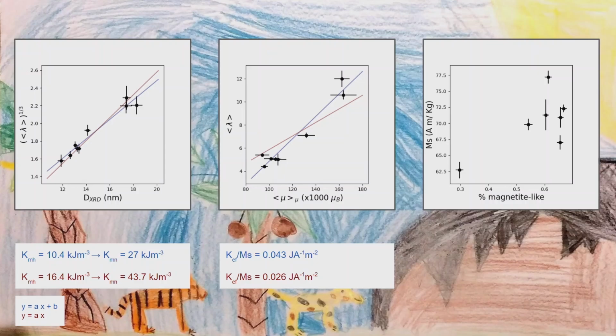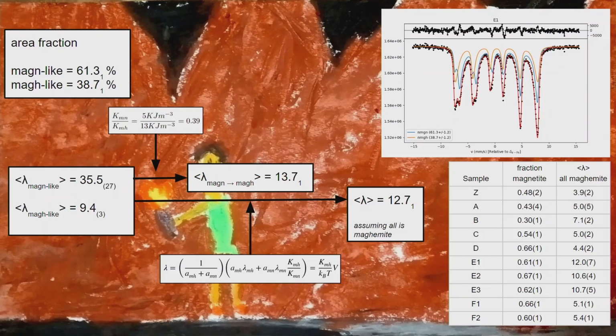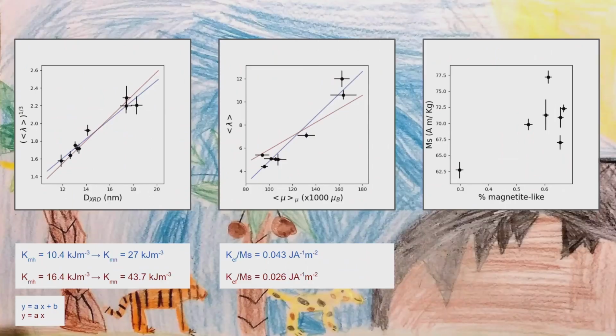From the correlation, we can obtain information about the effective anisotropy constant, and from the value we obtain, in fact, we obtain the effective anisotropy constant of the maghemite because of the construction. But with this easy or assumed relation, we obtain the other one. And both are very near the ones in the literature for nanoparticles. There is some difference if you make the correlation using a line that has a free, independent value or not, but both are in the same range.